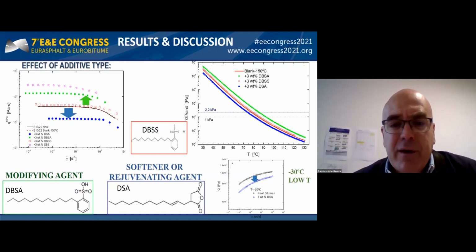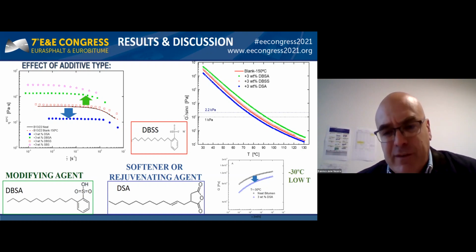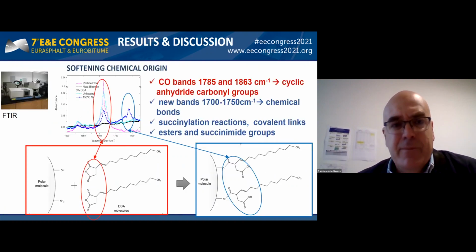Finally, in the bottom right corner, it is important to note that at minus 30 degrees, DSA also gives rise to lower values of the complex modulus, pointing out a significant improvement in the low temperature properties, where thermal cracking usually happens. Therefore, it is clear that sulfonic acid-based surfactants work as a typical modifier agent, whereas DSA may be employed as a softening or rejuvenating agent.